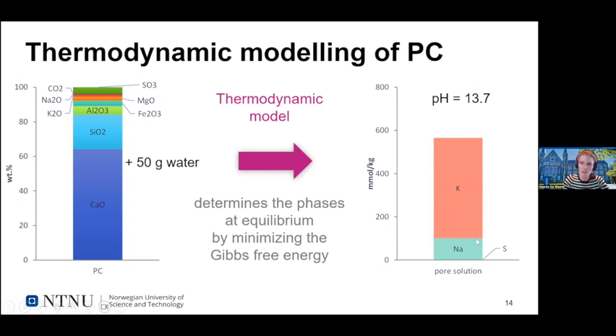You see that the pore solution, the main ions in it are sodium and potassium, and it leads to a pH of about 13.7. The other elements are there, but they're in much lower concentrations. So if you want to see how much calcium or sulfur, I would have to use a log scale to show these concentrations, but they're also there. So this is what I could do for Portland cement.